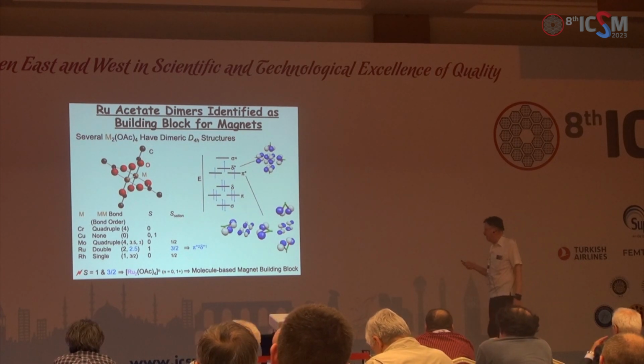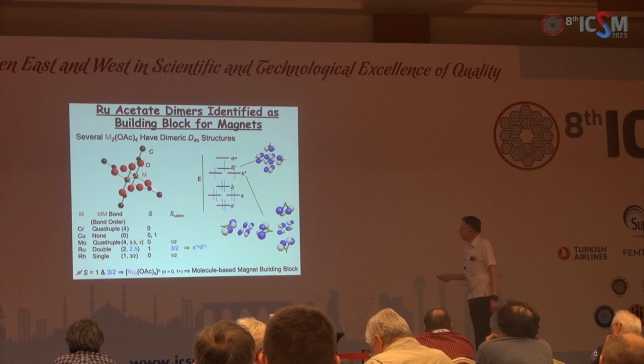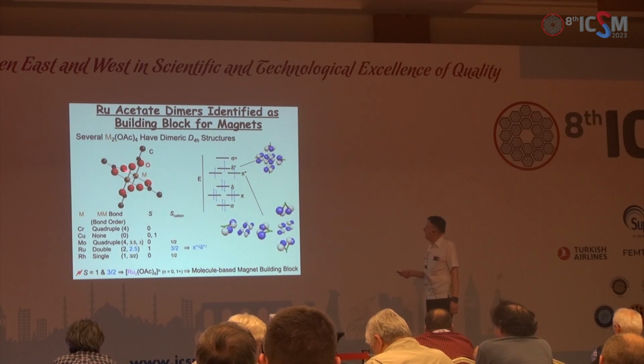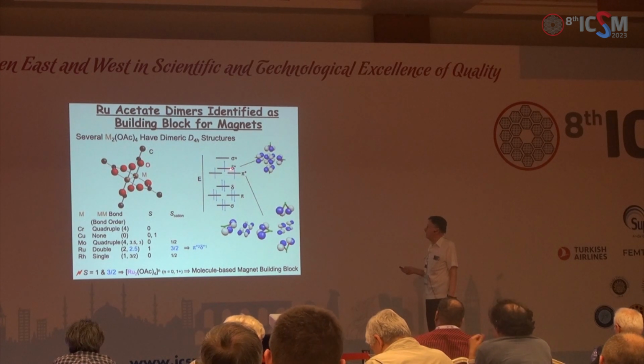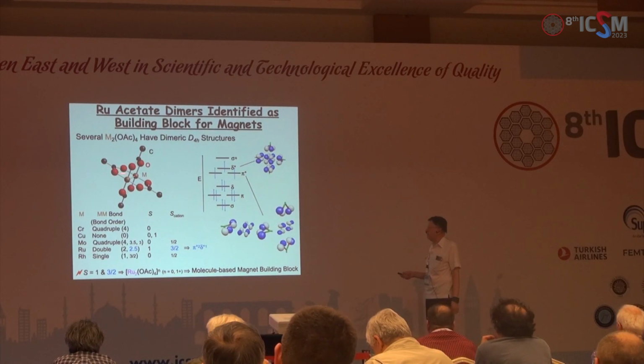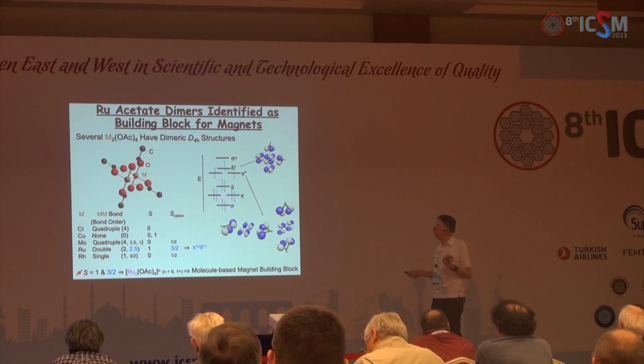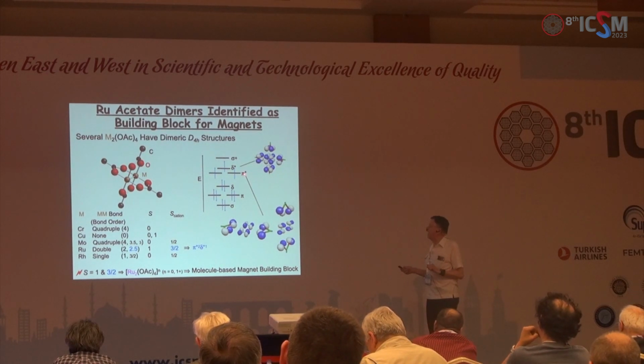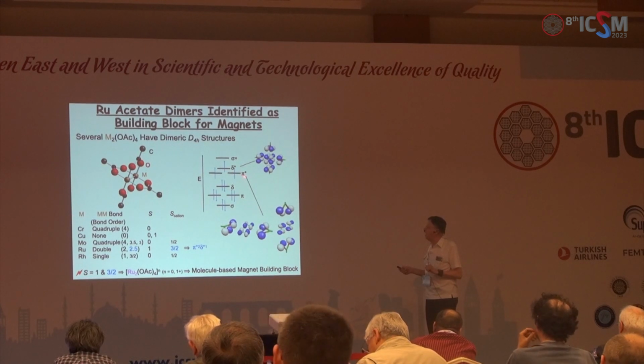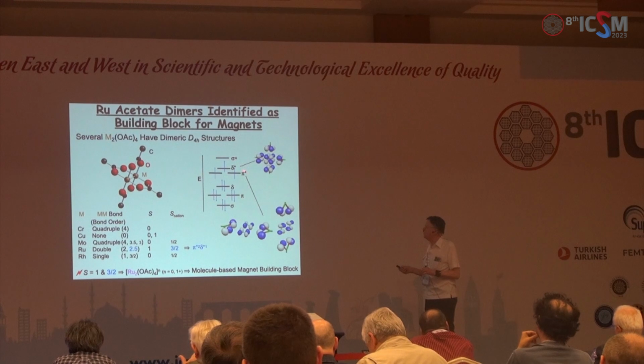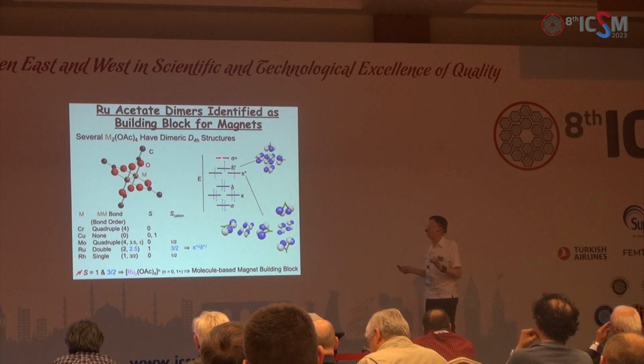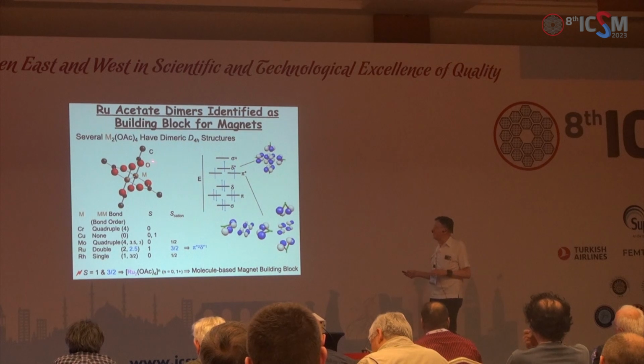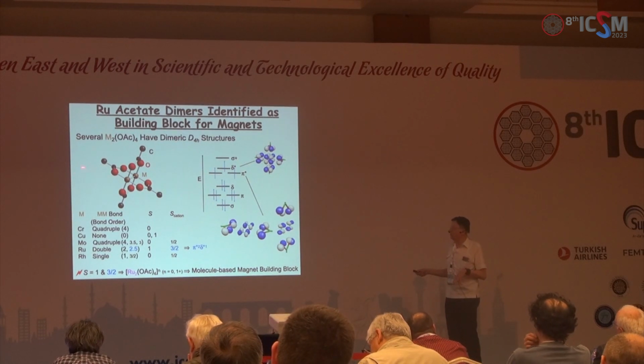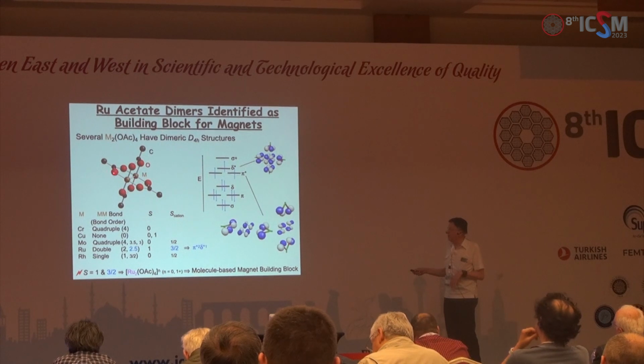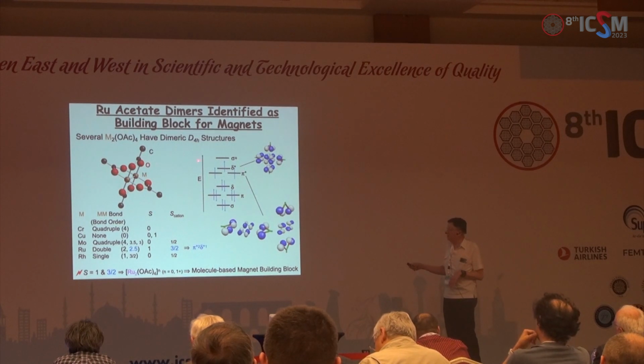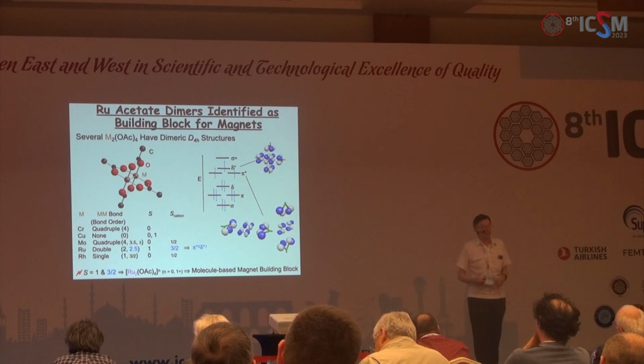If you have ruthenium in there, you actually have a double bond, and the electronic structure is such that there are 3 unpaired spins over these 2 ruthenium sites: 2 in perpendicular anti-bonding orbitals of pi symmetry, and 1 of anti-bonding delta symmetry. Now, as a coordination chemist, a physicist wouldn't appreciate this, but it should be 6 coordinate, and it's 5 coordinate—there's a vacant site on this side and that side, and we can use that to construct something.